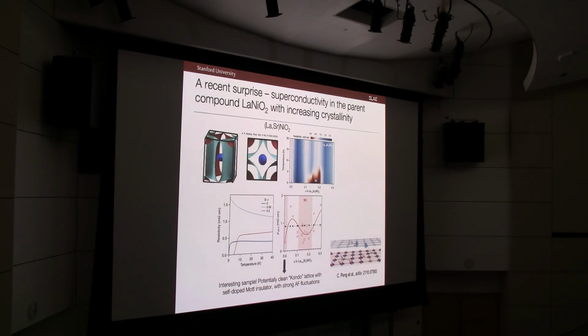Some of the things we're thinking about is that this is, as we have been discussing, apparently self-doped, and that this might be what we're seeing. It seems suggestive that we might be able to access a rather clean system, meaning in the absence of solid solution type of disorder, a rather interesting soup. I took this from a local theory paper, which illustrates the ingredients. You have the nickel-nickel lattice, the antiferromagnetic fluctuations that I just showed you, but also cross-coupling in this other channel to the rare earth 5d band, for example.